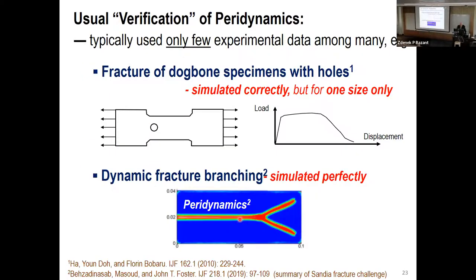The usual verifications of peridynamics were dogbone specimens in tension, with or without a hole. So there was an international exercise, called the Sandia challenge, that's it. And what is measured is how the crack evolves, and also the load-deflection curve. And again, peridynamics can fit this very well, including the dynamic effect, branching for a fast crack. And these are basically the verifications that are available in the literature.